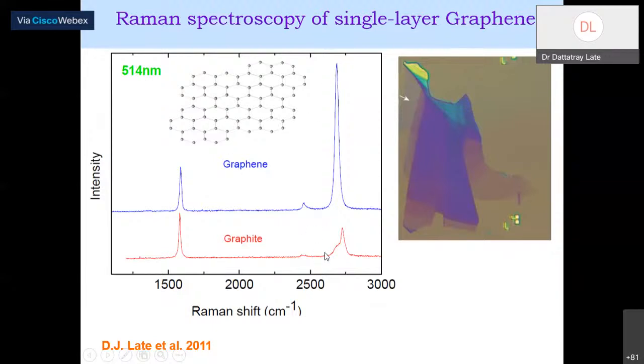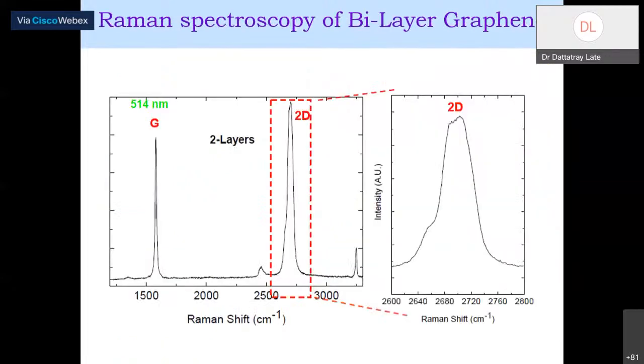You can see in bulk graphite there is a multi-mode spectrum available. In a single-layer monolayer graphene sheet, there is a single peak, a single spectrum available. So this also gives you a distinguishing feature whether your sample is monolayer or multi-layer graphene. Of course, there are some changes in one layer, two layer, three layer, multi-layer graphene. By these distinguishing spectra, we can identify whether your graphene is one layer, two layer, or multi-layer.